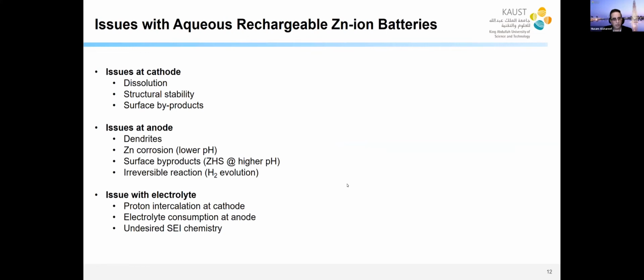Okay, so what are the issues with the zinc ion batteries? Many. Okay, there are issues at the cathode. For example, cathode dissolution. Manganese oxide is notorious for this problem. Because zinc, as I will show, even though the ion itself is small, it is hydrated by 6 water molecules. It actually becomes large. So when you intercalate it in the cathode, you cause structural instability in the cathode, and it doesn't last very long. There's also surface reactions. At the anode, it's even worse. You have dendrites, you have corrosion, you have byproducts, and you have irreversible hydrogen evolution. Okay. So in the electrolyte, we also have proton intercalation at cathode, we have electrolyte consumption, and we have undesired side chemistry.